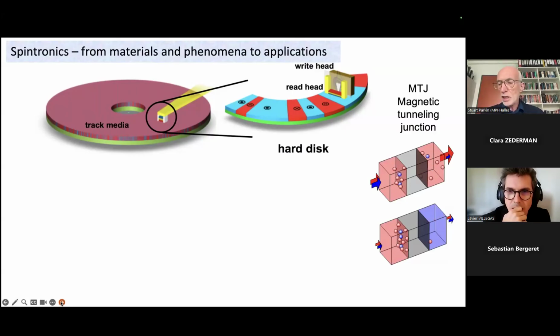And so here you can see a cartoon of a tunneling junction with two magnetic layers, blue and red, separated by the gray layer. And that gray layer is a very thin insulating layer formed from magnesium oxide. When you extract the current from a magnetic layer, it's automatically spin polarized because of the spin-dependent density of states in a ferromagnet, because of broken time reversal symmetry.